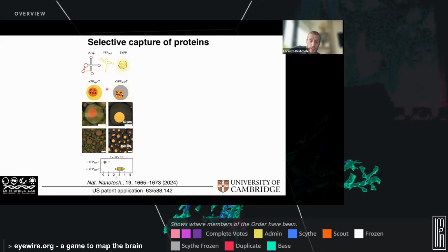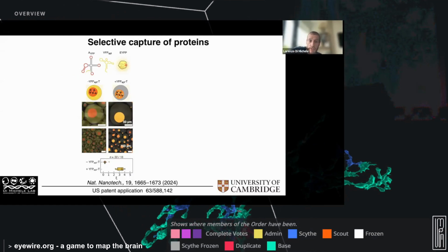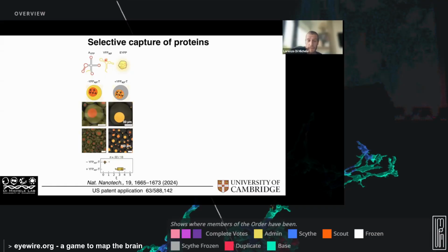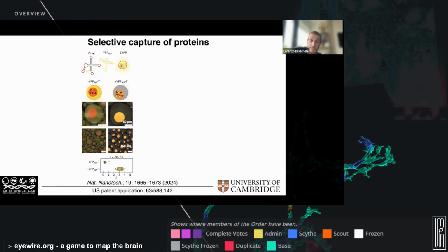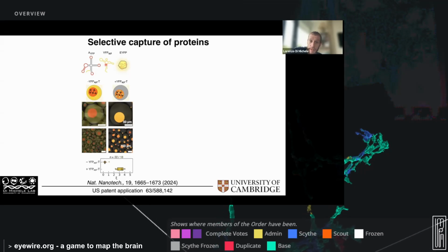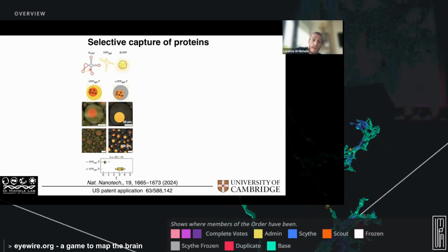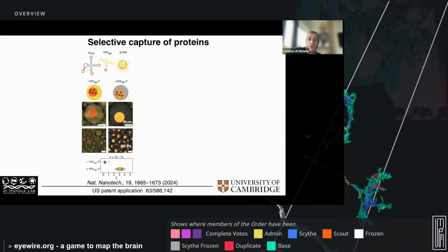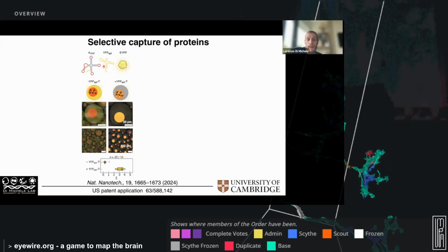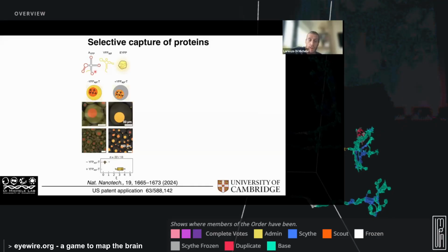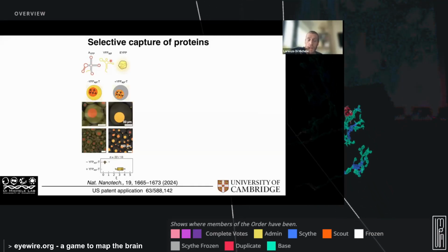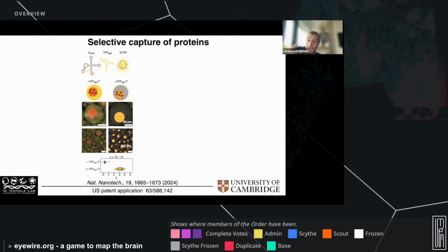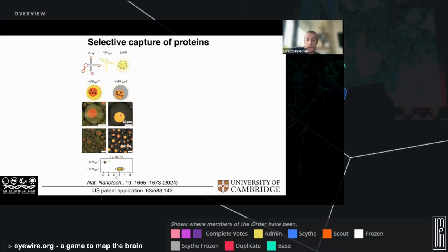It's very easy to capture proteins within these RNA condensates. All that you need to do is to consider a protein that can be targeted by an aptamer. In this proof of concept example, you have YFP and you have an aptamer that can bind the YFP, so that's an RNA aptamer. Then you can engineer your building block with an overhang that is complementary to another overhang on your aptamer. Then you co-express your condensate building block, the aptamer that binds to it, and in the presence of YFP, you can see that the YFP gets captured within the RNA condensate.